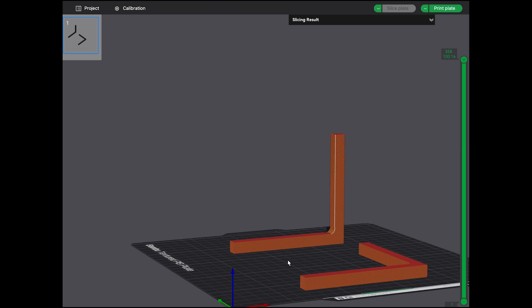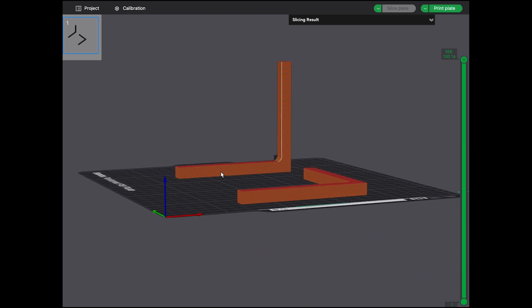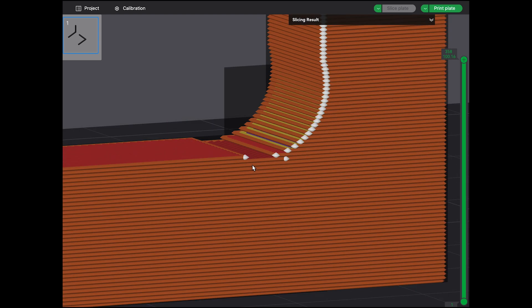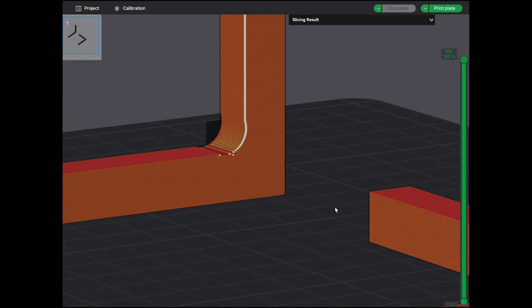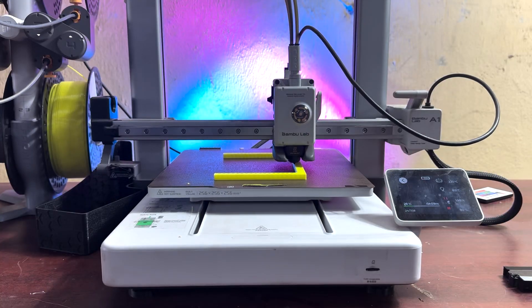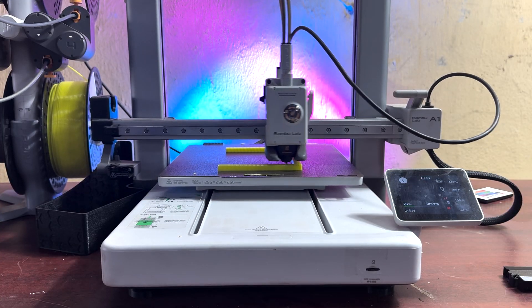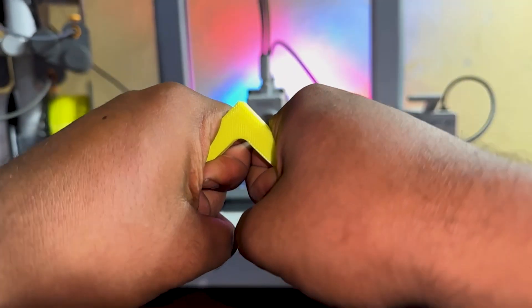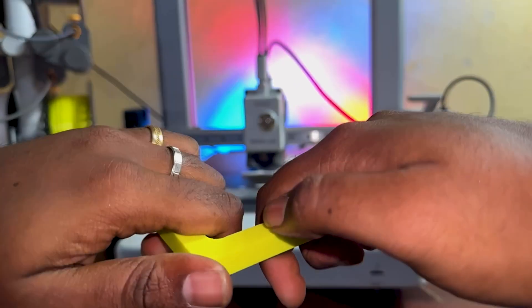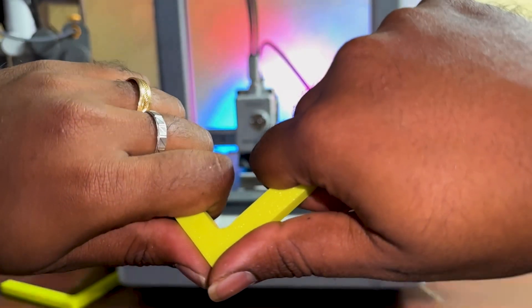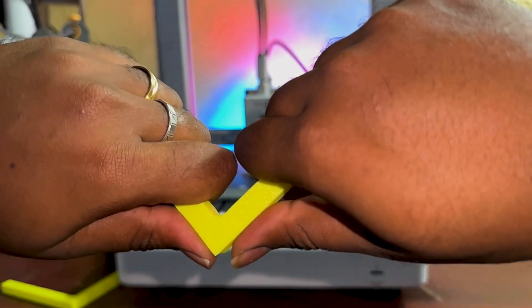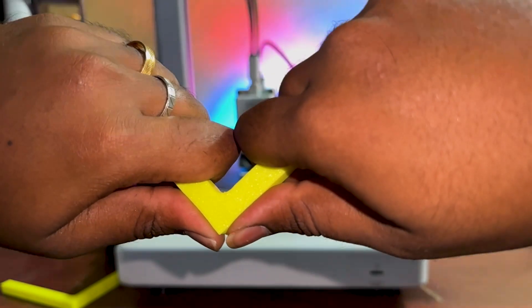Here are some quick tips when designing the part for maximum strength. This is called design for additive manufacturing or DFAM. Using a curved fillet rather than a sharp 90-degree angle can help to improve the strength. Here's an example of a part printed with fillet, even with the part having bad orientation while printing, it holds up better than the 90-degree part. This is because the stress concentration gets evenly distributed.